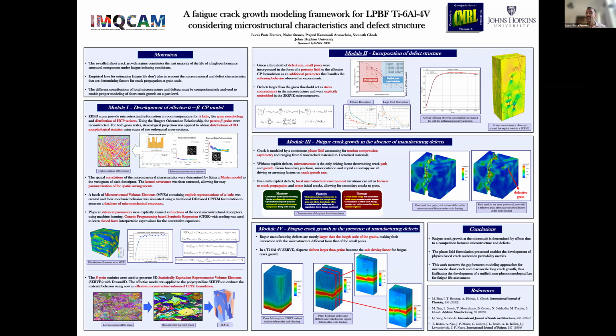Yeah, so the trick is that when we model the crack path with phase field, we take into account all of the energies that would drive the crack. So in some arrangements of the microstructure, those energy levels might be more inducing of crack growth than maybe the surroundings of some defects. Because of that, we cannot say for sure that having a defect is where the crack is going to grow, because the microstructure around the defect might be detrimental for the evolution of these energies. So other regions where, due to the loading and all, we have a higher energetic state for crack propagation, that's where our model is going to tell where the crack grows.